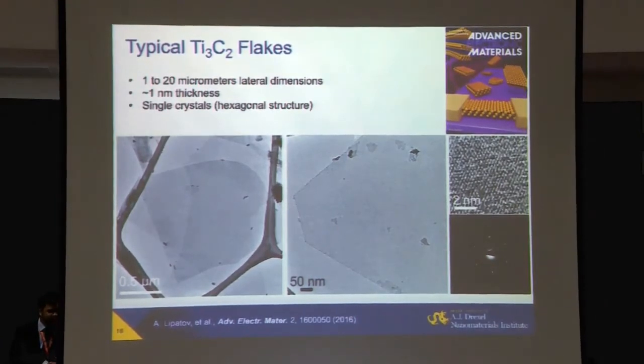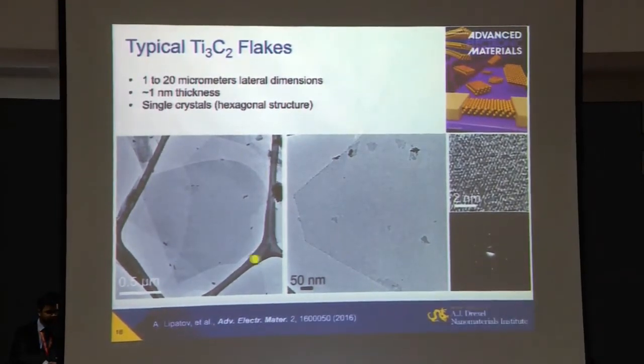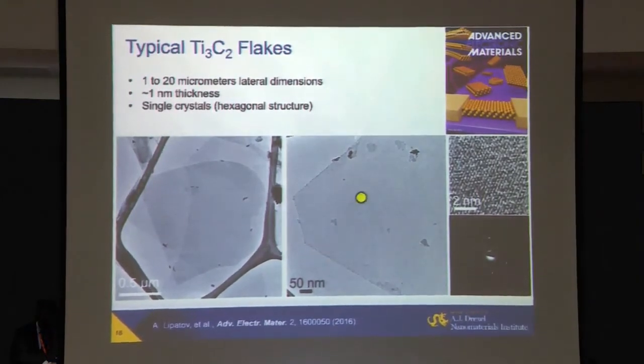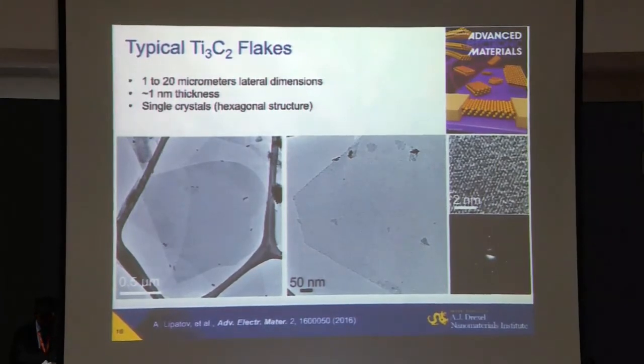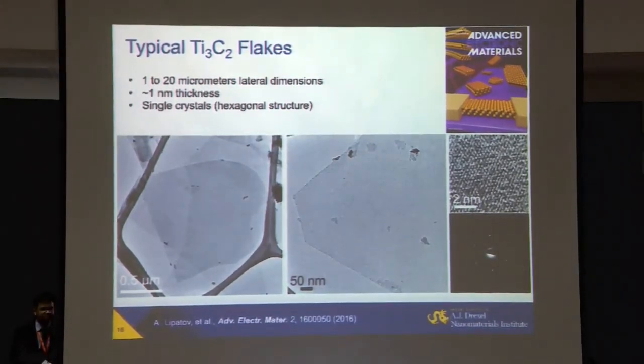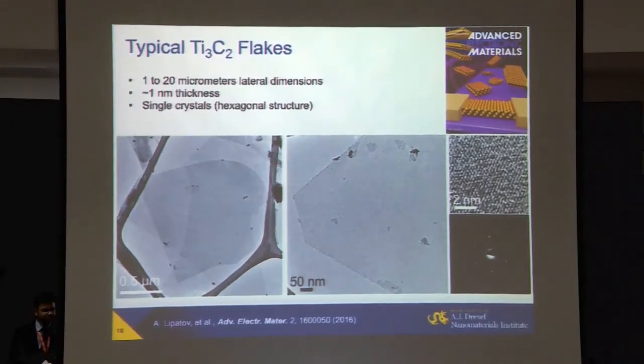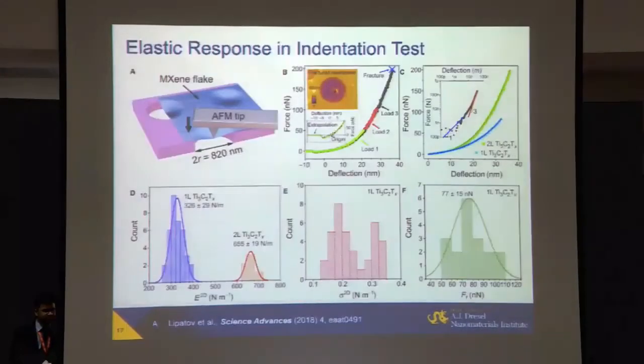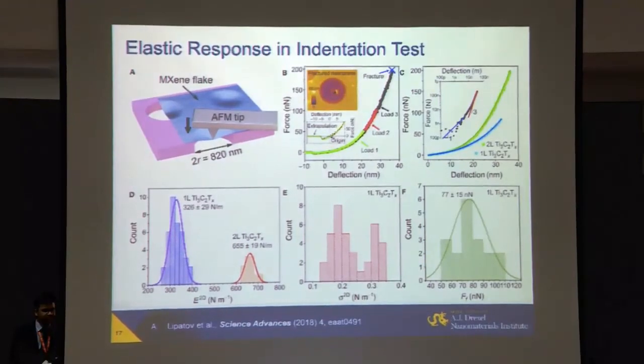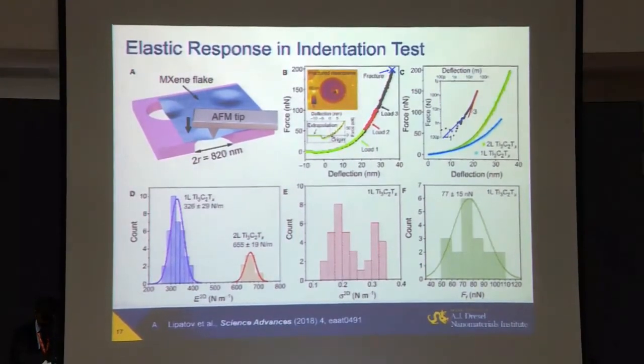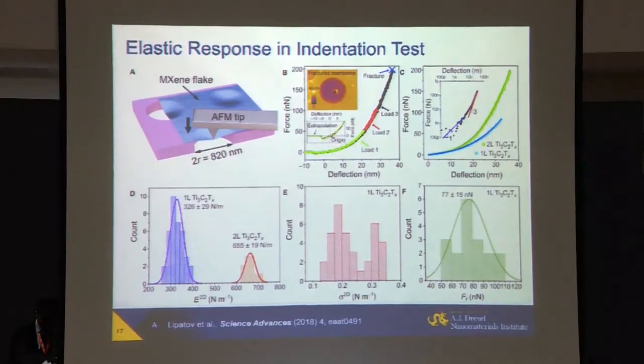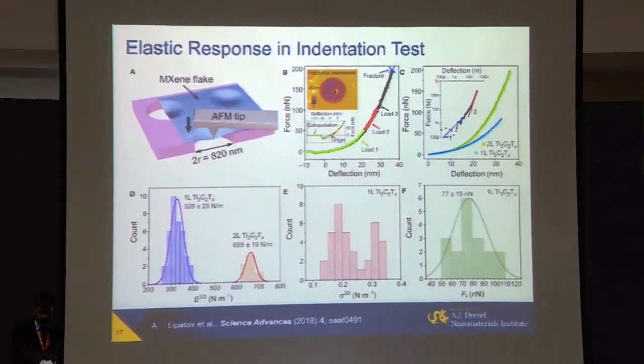But what is interesting is that they may look very similar to what you see from some graphene or moly disulfide, but you will not get a picture like that, for example, because graphene will right away drop. It's flimsy, it's thin. Bending rigidity of MXenes, because of just a few atoms thick layer, is significantly larger, so it can actually stay suspended and keep the shape much better. And actually, it is pretty tough because carbides of transition metals are known and used, for example, as very resistant materials. Cutting tool, titanium carbide, tungsten carbide.